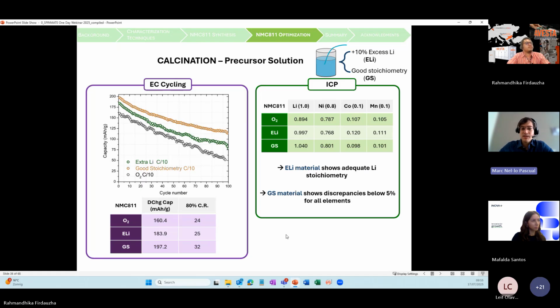So first we started with the ICP, and we saw that for the excess lithium sample, now the lithium is in the right concentration. It's close to the value of 1, but even if we add the lithium, we still saw this inhomogeneity in the cobalt and manganese composition. But in the good stoichiometry sample, we saw that now all the elements are in the right composition, showing discrepancies below 5% for all these elements. So in the end, we have a material that has the right stoichiometric ratio. And if we compare this with the ICP obtained for the commercial sample, move to the next slide.